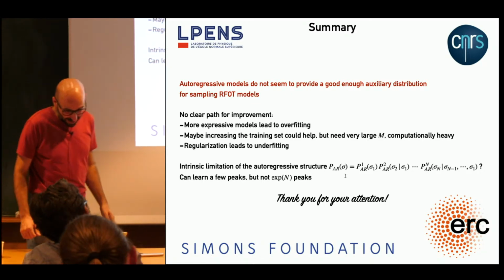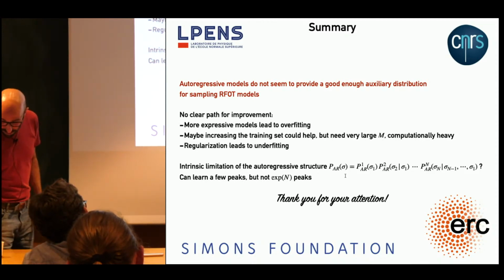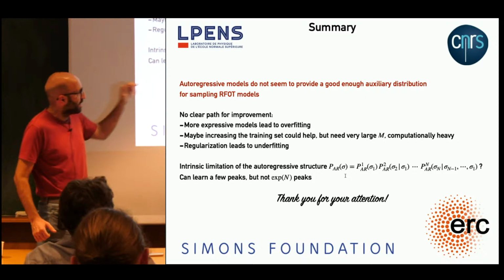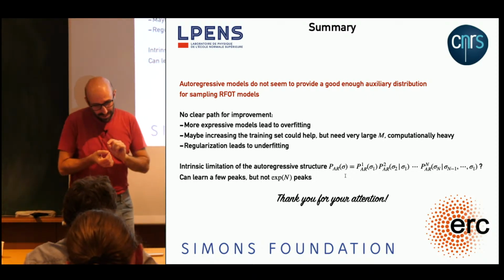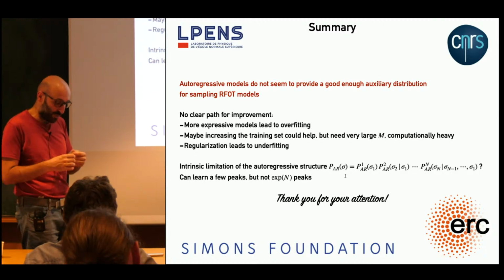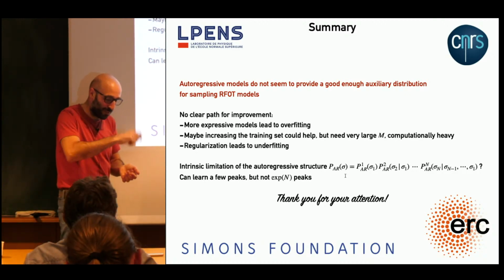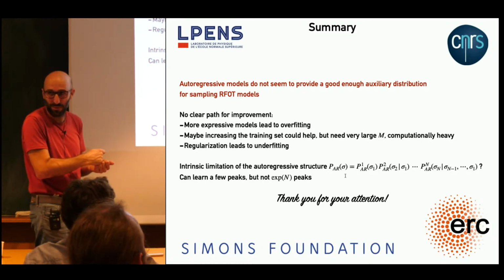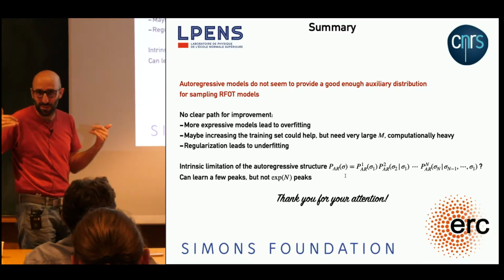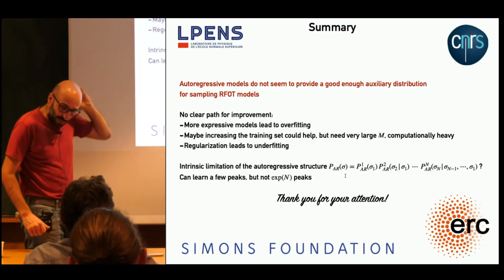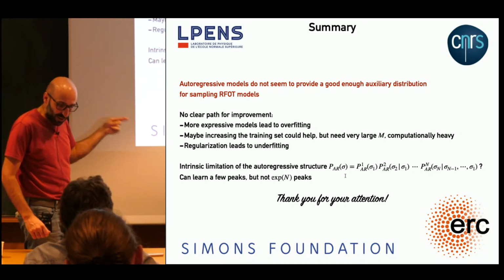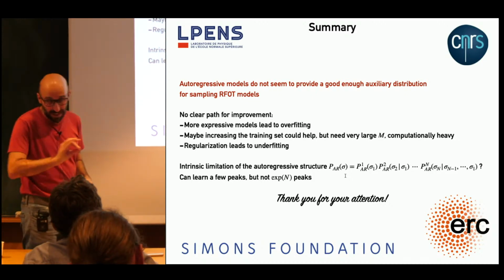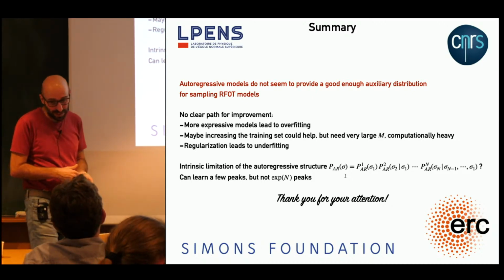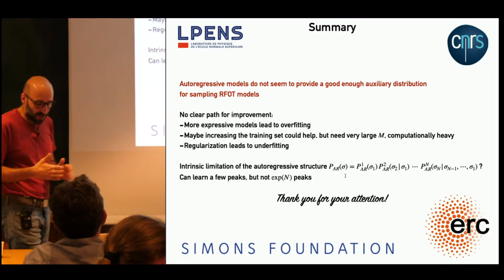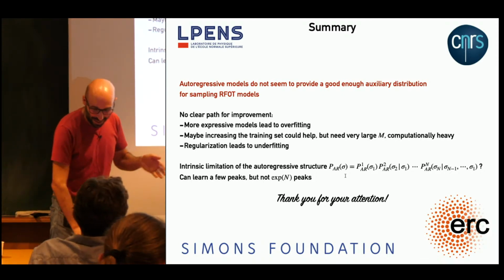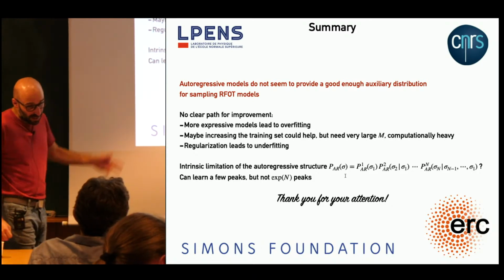So if you have ideas, well, what we are trying to do now is, instead of learning one model like this, try to learn a kernel that can propose moves. So you learn a function k(sigma, sigma prime) that proposes a move given the previous one, because here you are proposing a move without taking into account where you are. There is a paper that did again the spin glass using this approach, learning moves based on the current configuration, and it seems to work quite well. Not amazingly well, but it seems to work in that case. So it should be worth testing.